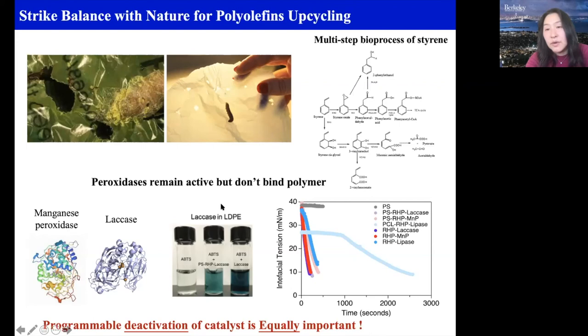We have a very thankful undergraduate student from Seoul National University, who wondered about the chemical structure and size of the degradation residue. May I consider it monomer-like level, and would it be capable to restore the residue and recycle it? Yes. If you look at LCMS, we basically get monomer, dimer, and trimer, and we actually polymerize them into polymer, and we can redegrade it. We also incubated the degradation byproduct with cells, and they act as food for them.